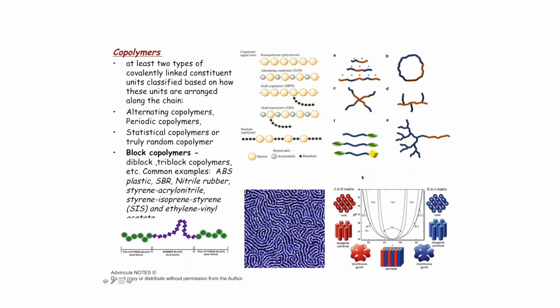But synthetically, one can have a hydrophilic block and a hydrophobic block. One can synthesize a diblock, a triblock, a star copolymer branch, or a linear branch. All of this makes up for a very interesting phase behavior or surfactant stability as well. In fact, polymers are considered very stable surfactants versus small molecule surfactants. In other words, polymers can be used at a higher temperature, pressure, or conditions that a normal small molecule surfactant will easily degrade or have a lot of dynamic properties.